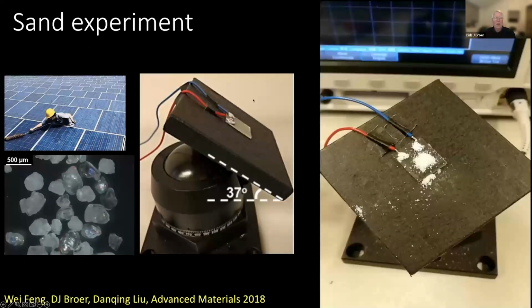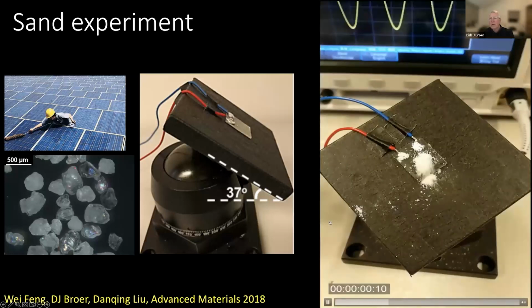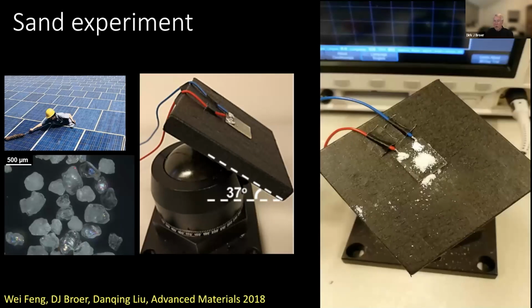And this is actually what we would like to use to make a self-cleaning surface, for instance, potentially for cleaning of solar cells. When they are subjected to a sandstorm, for instance, they are covered, and then you have to clean them again. But if you have our system, potentially, we have not done it on this large scale yet. If you have sand on the surface, and we use this model sand and apply the electric field in the system here, then you see that you can directly remove the sand from the surface just because of the dynamics in the surface.